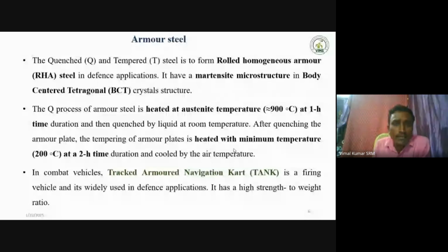Armor steel is a quenched and tempered steel, a form of rolled homogeneous armor steel used in diverse applications. It has a martensitic microstructure in a body-centered tetragonal crystal structure. Generally, it is prepared by the quenched and tempered process. Quenching is nothing but heating up to 900 degrees Celsius for 1 hour. Then the armor plate is tempered at a minimum temperature for 2 hours and cooled by air. In this condition, EN24 steel is converted into armor grade steel. It means the mechanical properties and microstructural characteristics also change to higher values. So in this condition, the strength to weight ratio is increased as compared to normal grade steel.